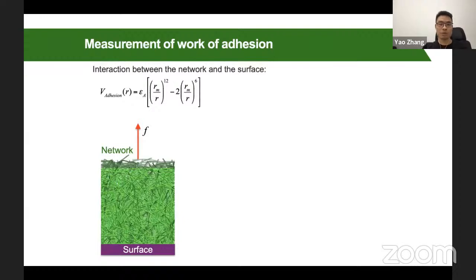Now we have a network. One test is the ability of adhesion. So we let the fiber adsorb on the surface. In this case, we just set up the adhesion between the network and the surface using a simple algebraic potential. If we tune this constant epsilon A, then you can tune the adhesion ability between the network and our surface. Now we try to apply a force F at the top of this network and try to detach this network from the surface. So what will happen?